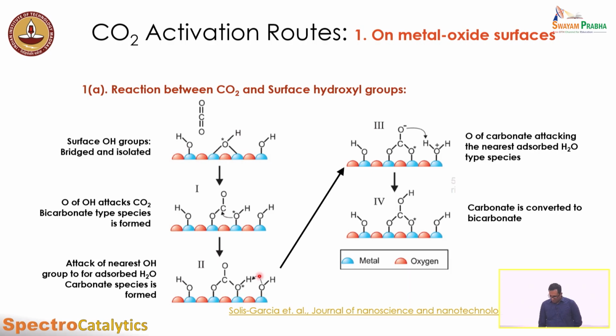Then what happens if we have a neighboring OH group? The oxygen from the neighboring OH group attacks the hydrogen species, giving a carbonate species and an adsorbed water on the surface. At a later stage, the dangling oxygen in the reaction environment, having an extra electron, can attack the edge of this water on the nearby surface to form a bicarbonate species. So depending on the type of OH group present on the surface, we can have different reaction intermediates.